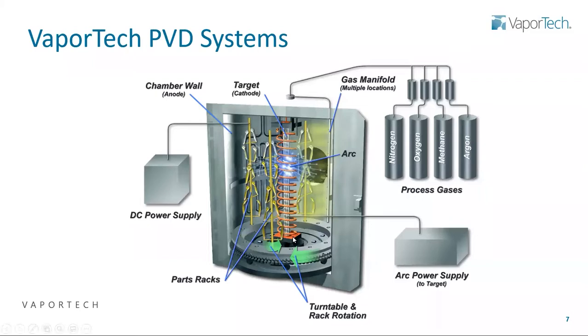We strike an arc on the surface, and that arc travels along the length and also around the circumference of that target. And where that arc is on the surface, it's actually vaporizing material and also ionizing material. It's ejecting material in 360 degrees around, and you have a very high energy of material coming off, a mixture of ions, which are energetic atoms that have had an electron removed, and that is getting deposited all around the inside of the chamber.